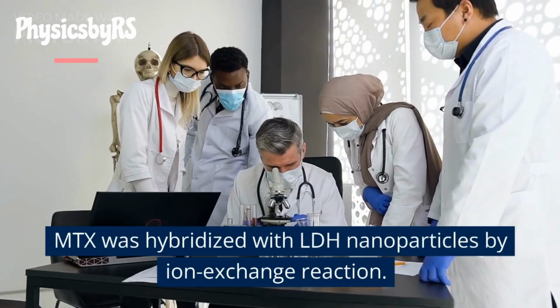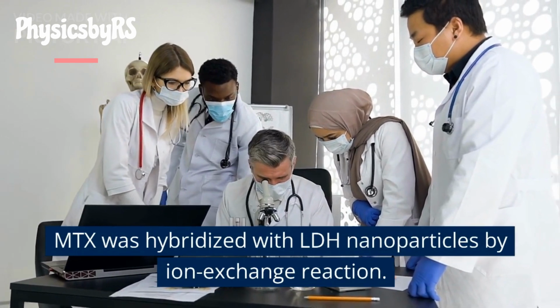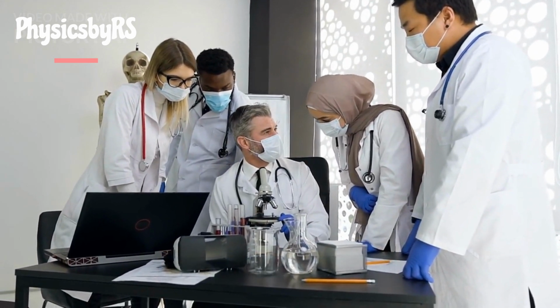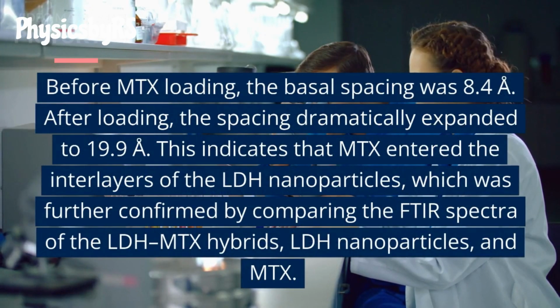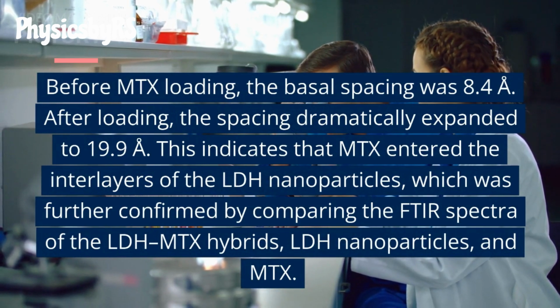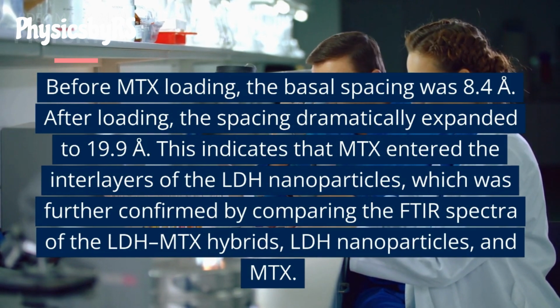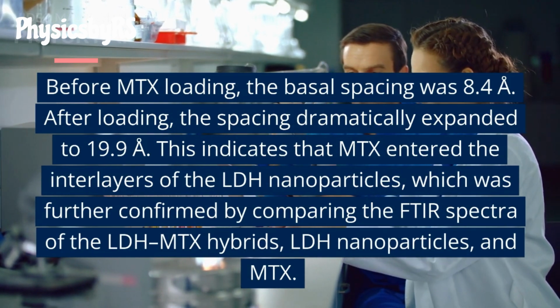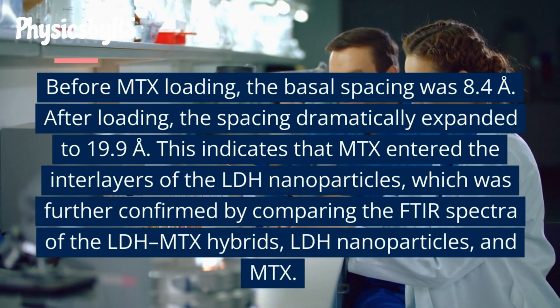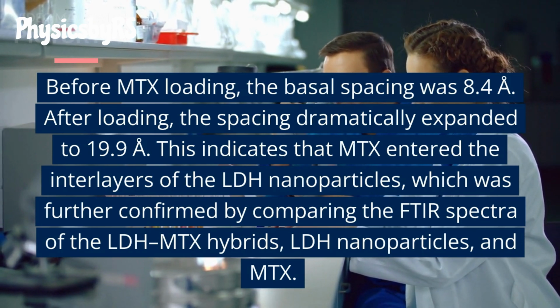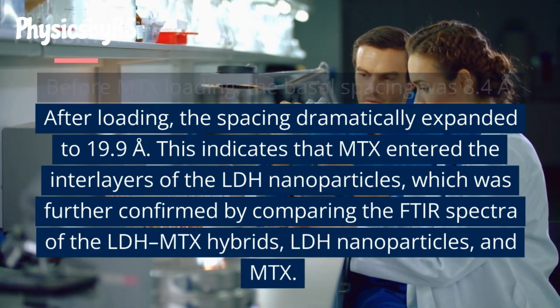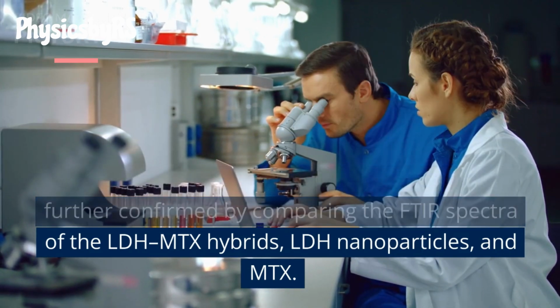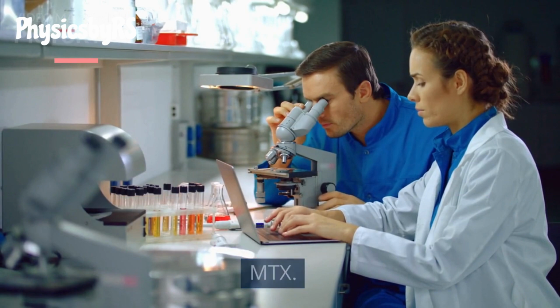MTX was hybridized with LDH nanoparticles by ion exchange reaction. Before MTX loading, the basal spacing was 8.4 A. After loading, the spacing dramatically expanded to 19.9 A. This indicates that MTX entered the interlayers of the LDH nanoparticles, which was further confirmed by comparing the FTIR spectra of the LDH-MTX hybrids, LDH nanoparticles, and MTX.